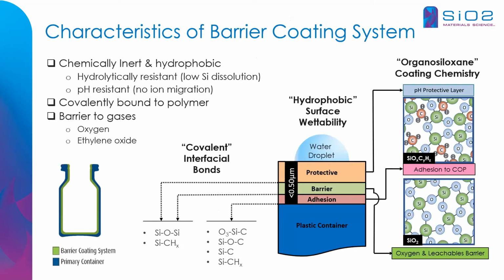Now, the barrier coating system is really a series of layers. It's what we call our tri-layer, but the overall thickness of this barrier coating is less than half a micron, so very, very thin. And that's a very important characteristic, because a plastic vial can deflect if you bend it. And so there was always a question of, hey, what happens if you deflect or bend the container? Doesn't it crack the coating? Well, a key point of this is being able to get a functional barrier that's very thin. And so at half a micron, it's a very functional barrier, but incredibly robust to mechanical challenges.